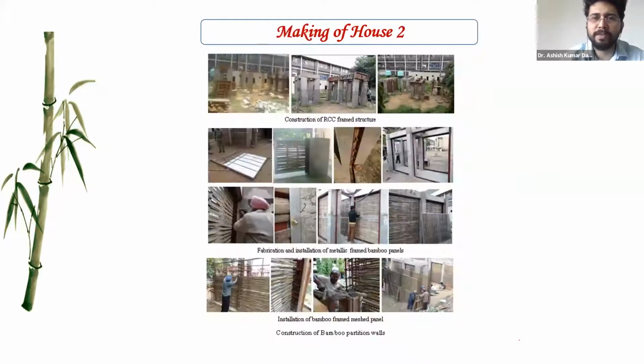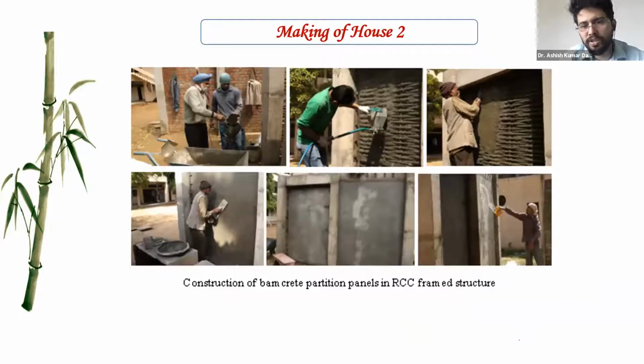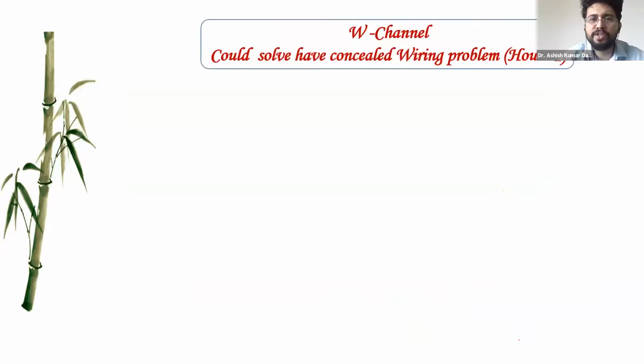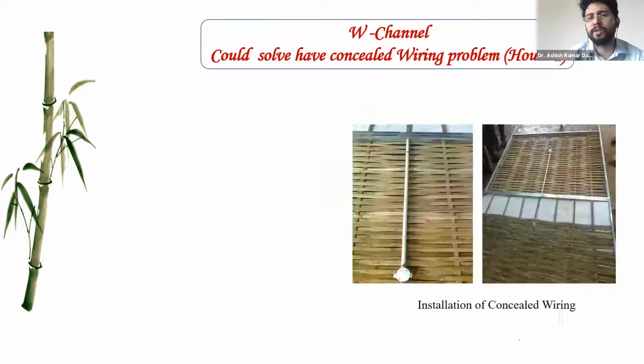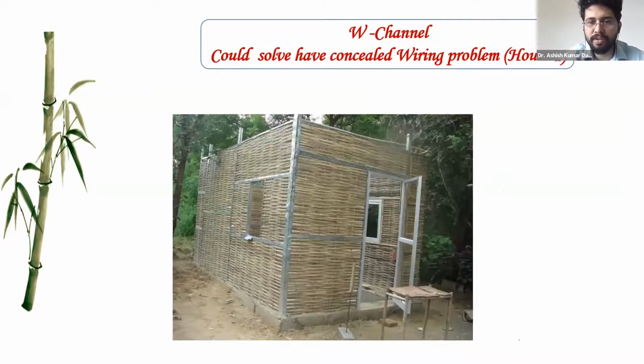And you can see after that, we started to study this bamboo panel technique in the RCC frame structure, how it can be implemented, and we started working on that. And this second house was plastered in the RCC frame structure using the mortar spray. In the twin leaf system, we solved the problem of concealed electric wiring, which is quite difficult in the case of the normal traditional Assam type house. To take this technology forward, we used this technique of the twin leaf system with the wiring passing through it. And this is the house that I have already shown.